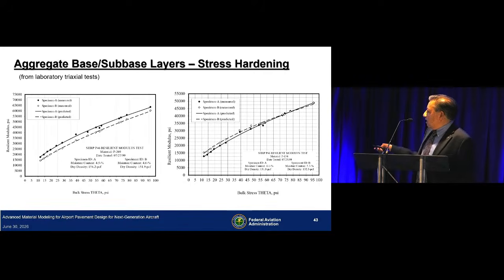On the right side is the chart for our sub-base material, which is P154. And in our studies, we used crushed screening. So it's a crushed material, and it also shows stress hardening behavior. Whereas, if you remember, in our design procedure we are using an equation to compute modulus of the aggregate layer as a function of subgrade CBR and the layer thickness, without giving any advantage to the quality of the material that we are using.